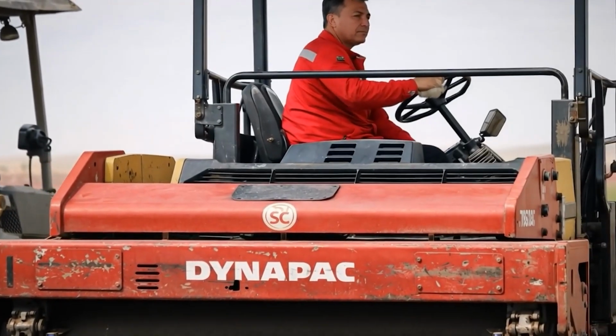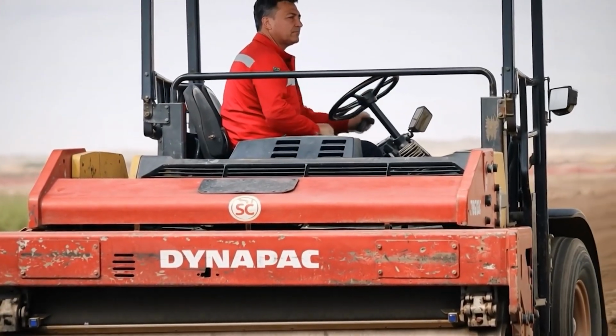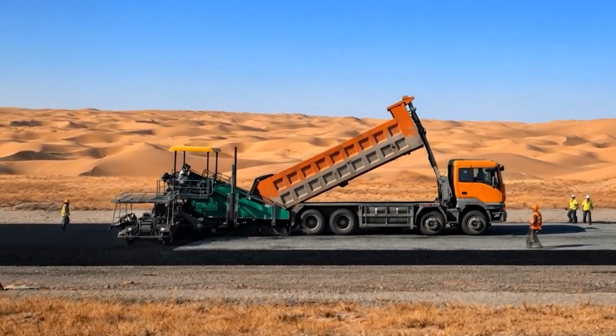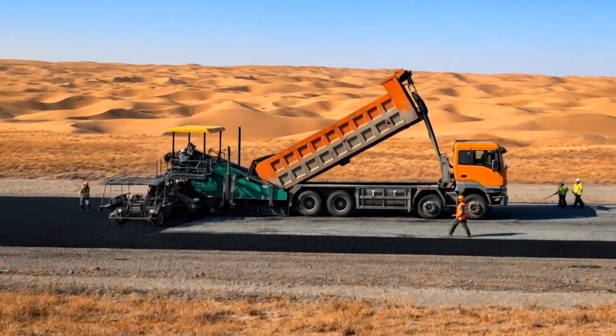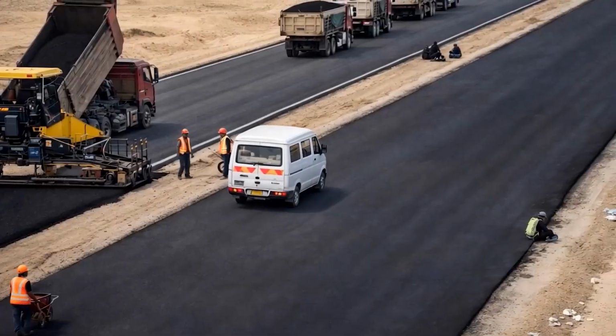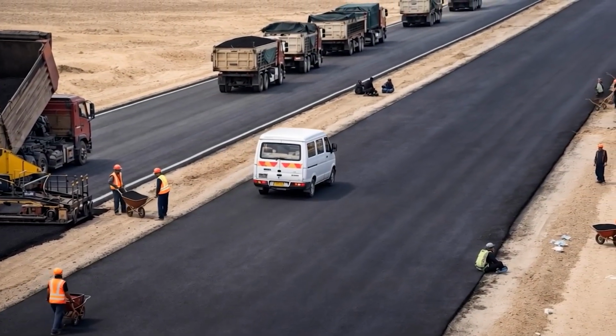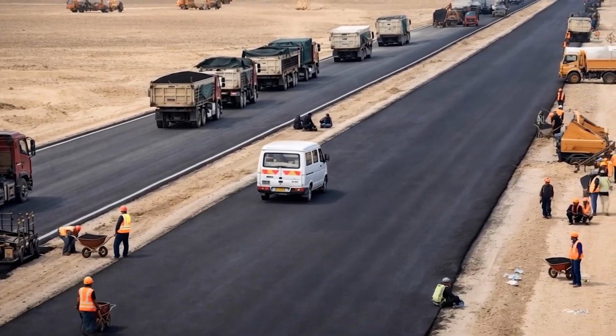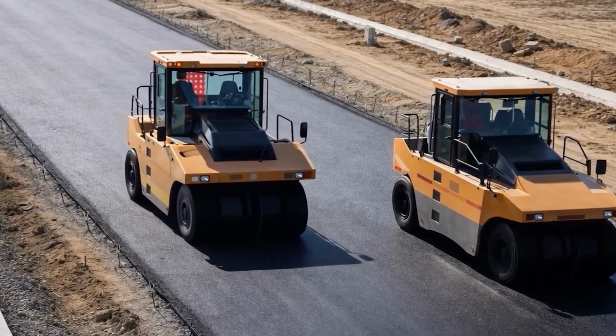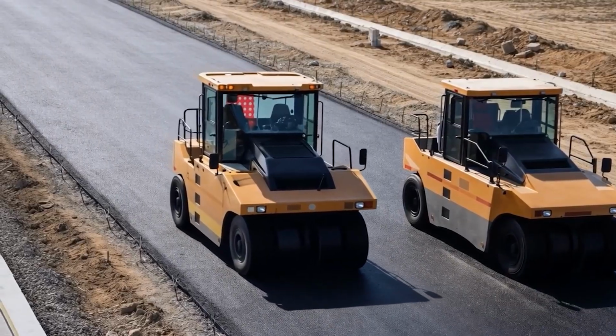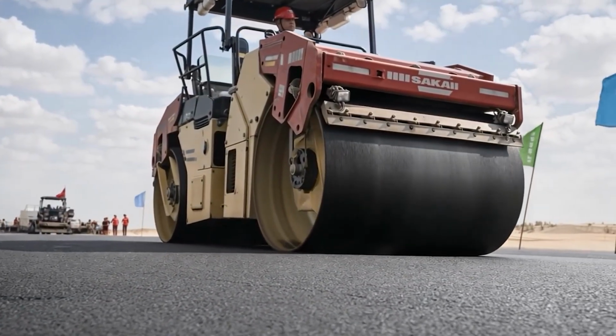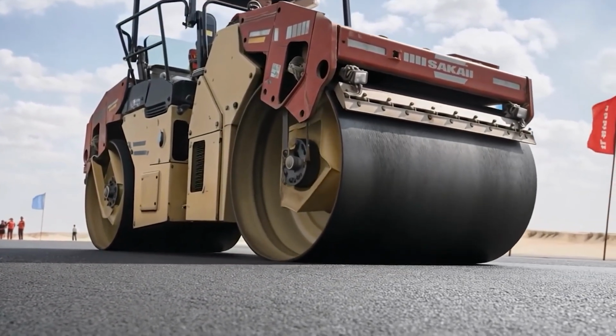Under the influence of the desert wind, the asphalt gradually cooled and turned into a perfectly even black ribbon. The pavement was designed for extreme temperature swings, from -25 to +70 degrees Celsius. The final touch was the application of a protective sealing layer. It gave the road a deep, dark shine and reliably protected it from moisture.